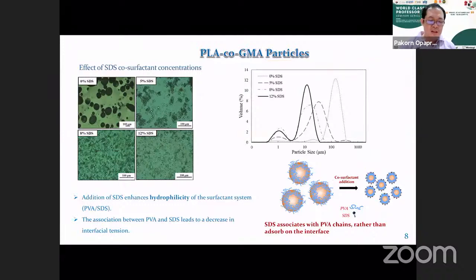And we also study the effect of the SDS content on the average size of the particle, and also the size distribution, how uniform the size distribution of the particle is. And we see that the amount of SDS that we add in plays a significant role in reducing the size of the particles, from bigger size until smaller one here.